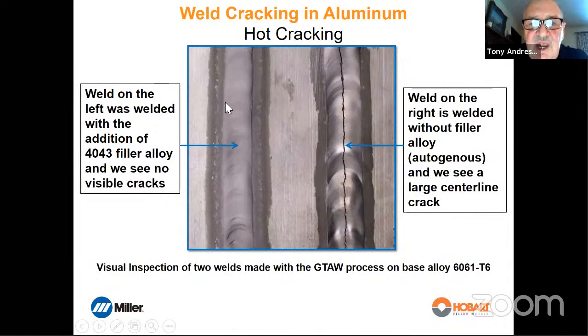Why? Well, we've changed the chemistry of the weld. This weld metal is now a mixture of the base and the filler alloy, and the filler alloy has changed the chemistry of the base and reduces the crack sensitivity. Here, the base is crack sensitive. You weld it with no filler, it's going to crack.